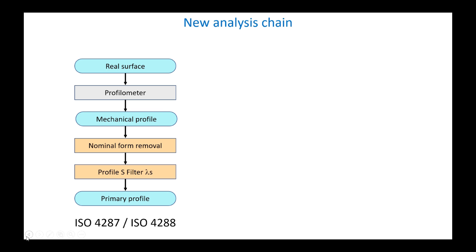A first important modification concerns the process of preparing the primary profile from the measured profile. Previously, the first step consisted of leveling the profile or removing its nominal form in the case of a non-planar workpiece. Then the micro-roughness filter was applied to limit the bandwidth in high frequencies where the specification does not apply.